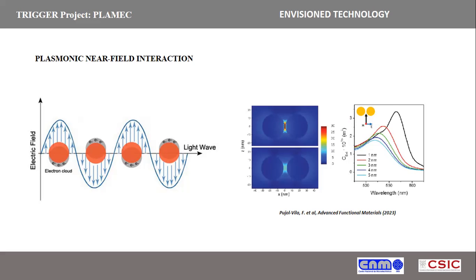So in this plot, on the right, you can see how the absorption spectra of a dimer of two distinct gold nanoparticles changes as a function of the interparticle distance, with a very, very high sensitivity to small changes in the gap distance. In this plot, it goes from 1 to 5 nanometers, and the color change is quite high.